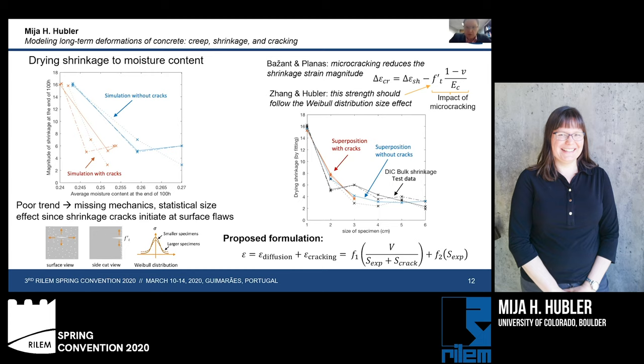So our proposition is that the proposed formulation for the strain and the introduction of the cracked surface area should be in terms of this composite function. One, to capture the effects of diffusion that has the volume of the surface of the outside of our sample plus the surfaces of the cracks in the denominator, as well as a second function that contains the strain due to the cracking that should be a function of the outside surface area coming from this surface size effect distribution.